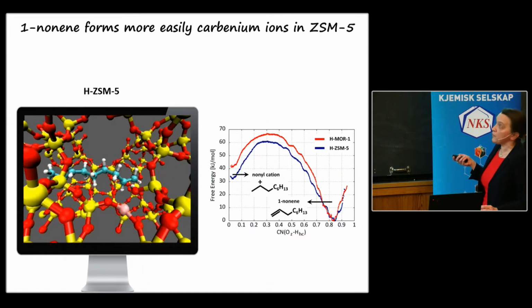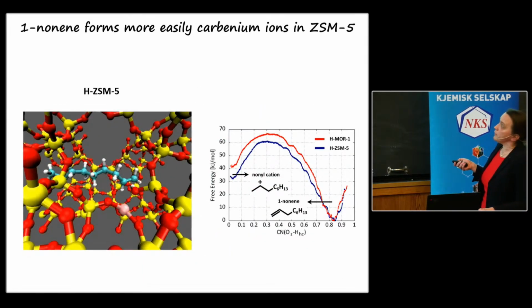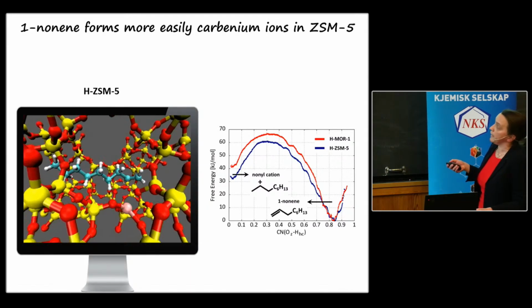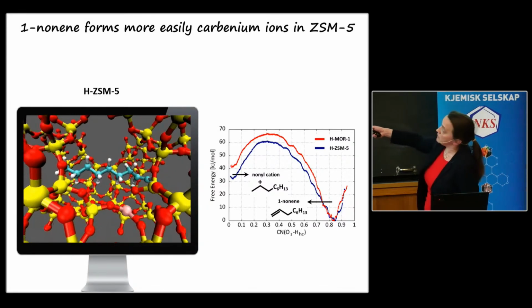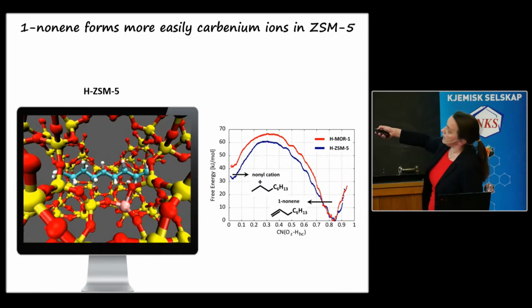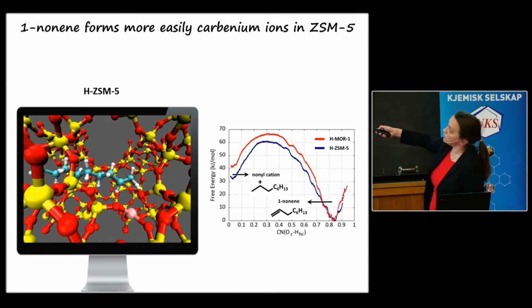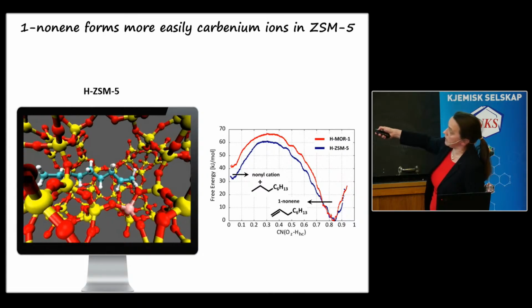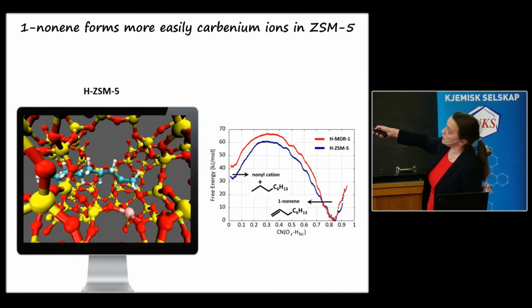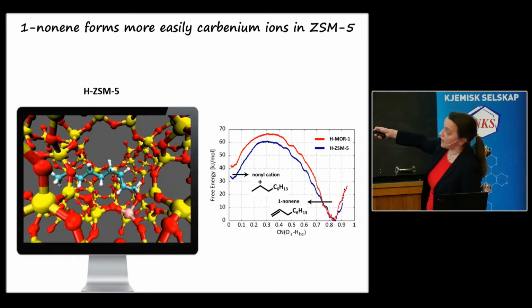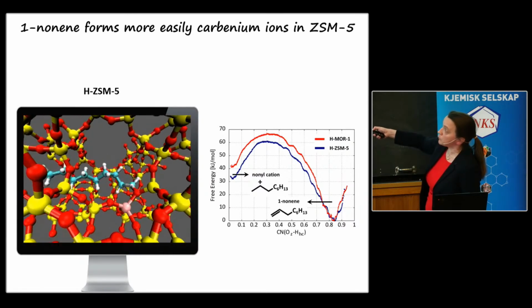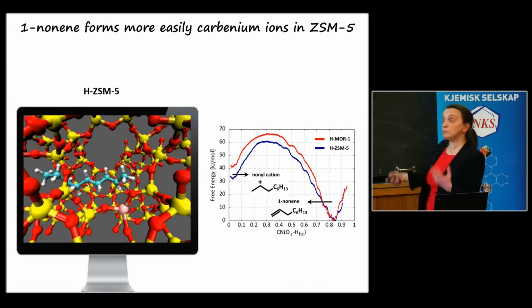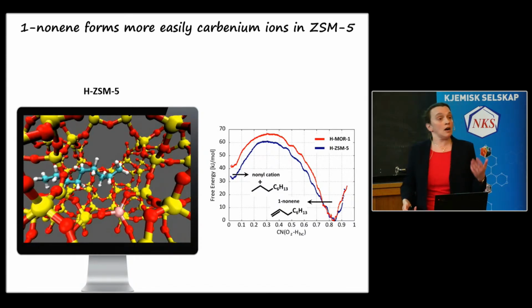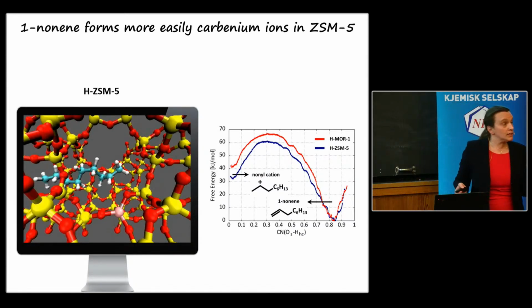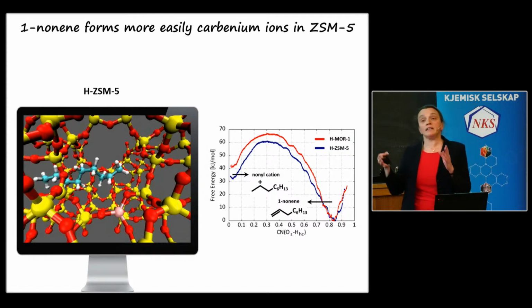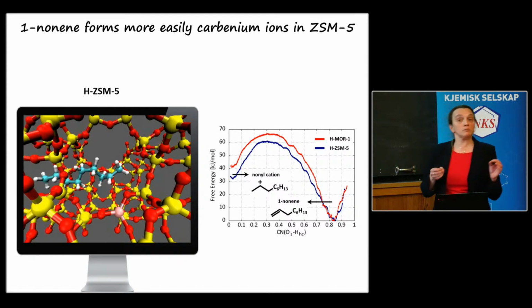If you look at ZSM-5, we see a different story. So here we start again from this nonene, and basically at a given moment you will see that here is the Brønsted acidic proton. You see the pi bond clearly in interaction, and it will indeed form carbenium ions here. And so ZSM-5 has the potential to form carbenium ions, and then from these carbenium ions, it can also make aromatics. So that's part of the explanation why ZSM-5 made aromatics and the other did not.